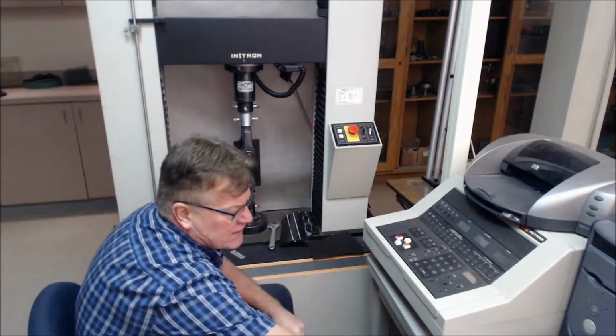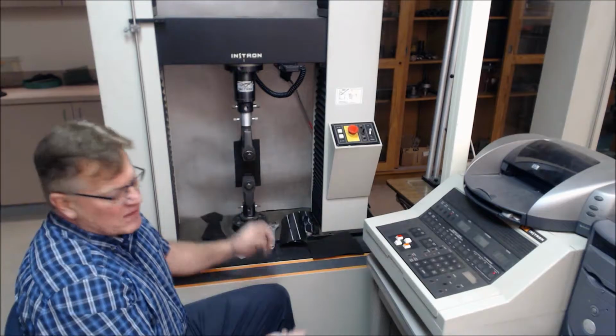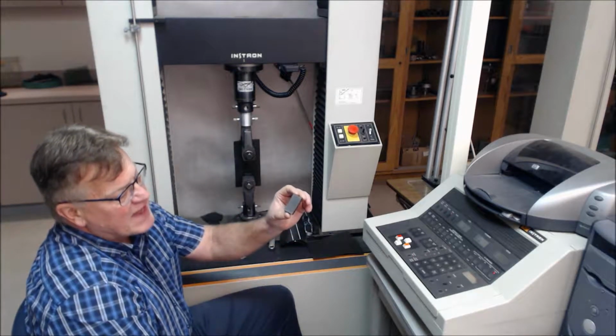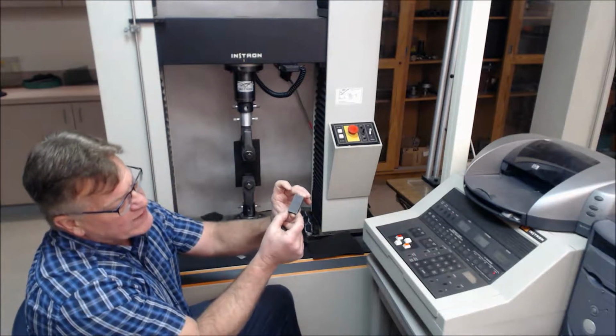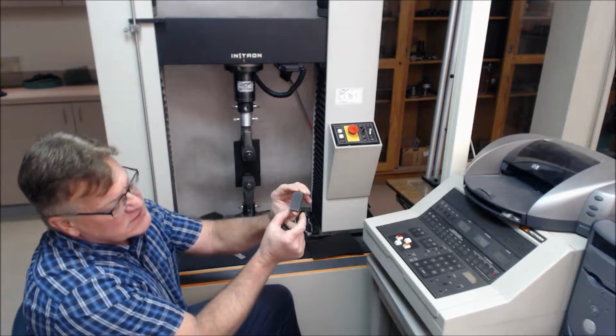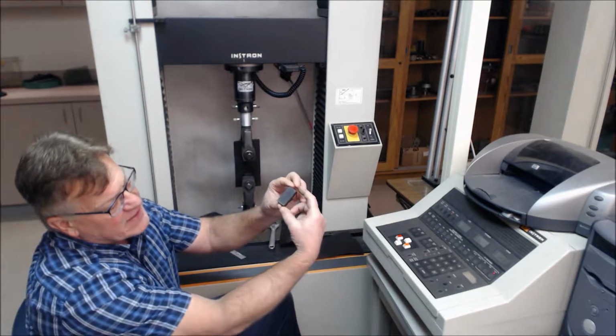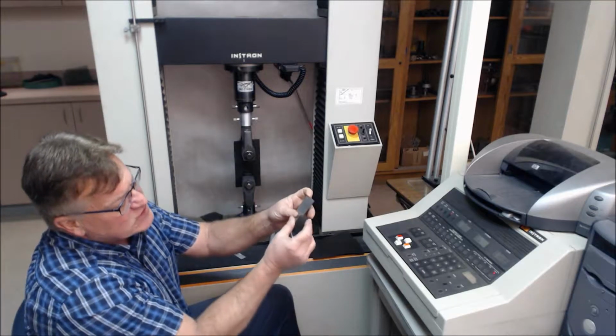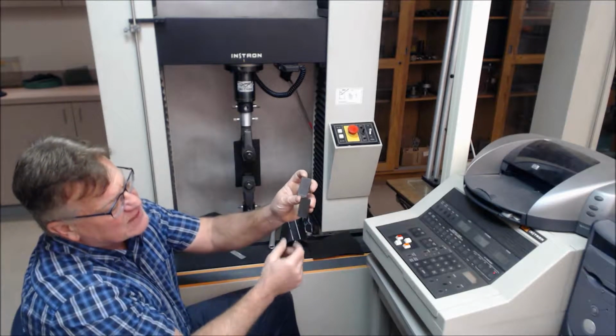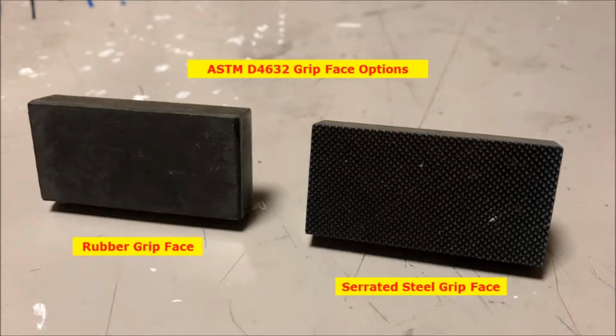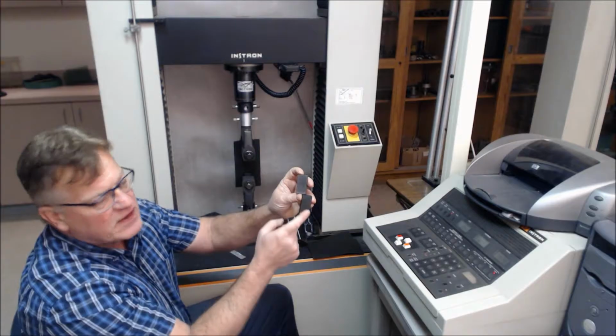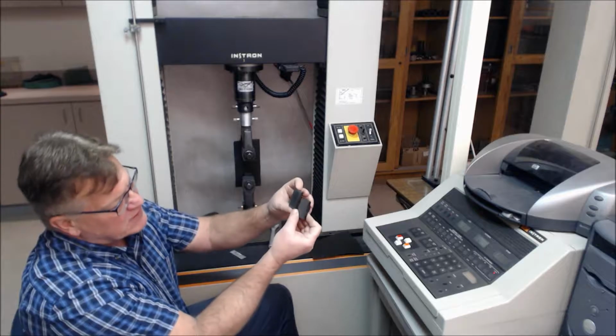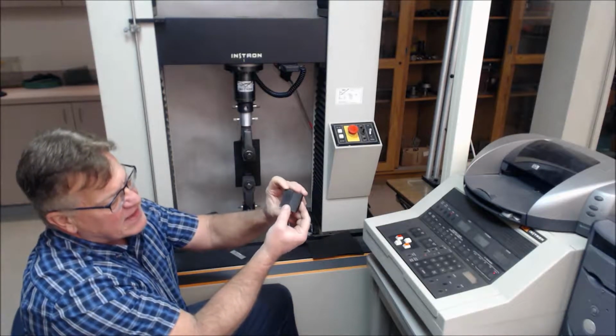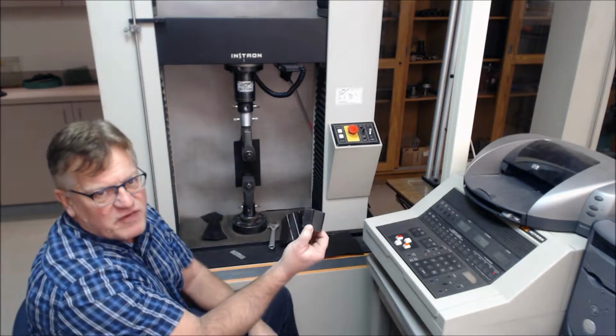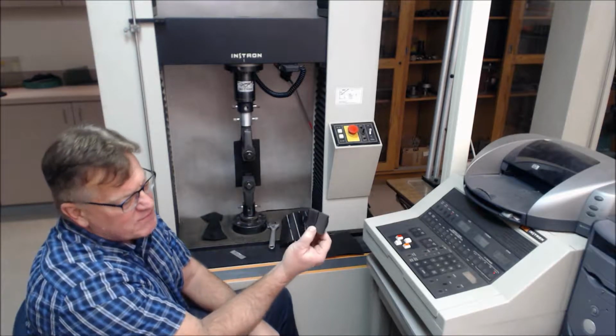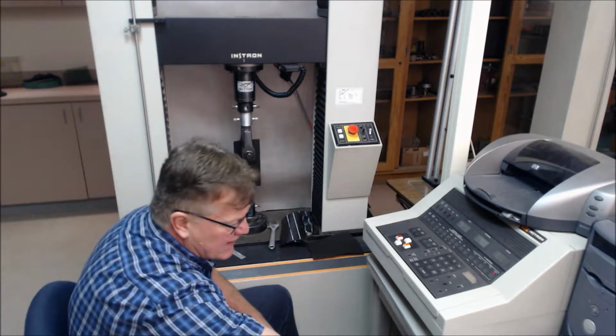The grips that you're using, these are Instron grips, but they're very important, the chuck that you have in it, which is 1 inch by 2 inch chuck, which is 25 millimeters by 50 millimeters. These chucks have different surfaces associated with them. This is a serrated steel, and this particular one is a rubber face. You'll go back and forth with that and try to maximize the face to the geotextile. It's by no means standardized in the standard.